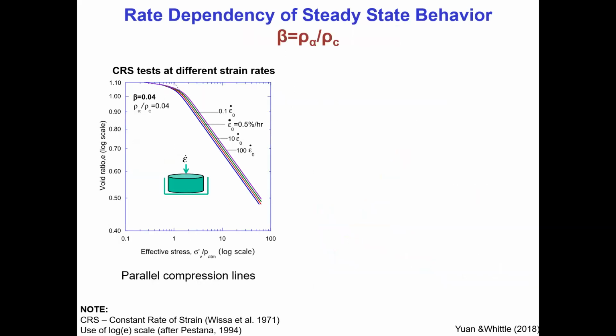Let me demonstrate this for you. You're going to see a series of figures. They are essentially looking at stress strain curves. So this is effective stress, void ratio or strain. What you're seeing in this figure is the compression of the soil under constant strain rate. So this is where Wissa comes back into the picture. This is his CRS test driven with some rate of strain. And you can see as I vary the strain rate, I vary the position of the consolidation line, the virgin consolidation line. So this is a control rate of strain where I made beta equal to rho alpha to rho sub C. This is the response that most people in the theoretical community refer to as an isotache behavior.